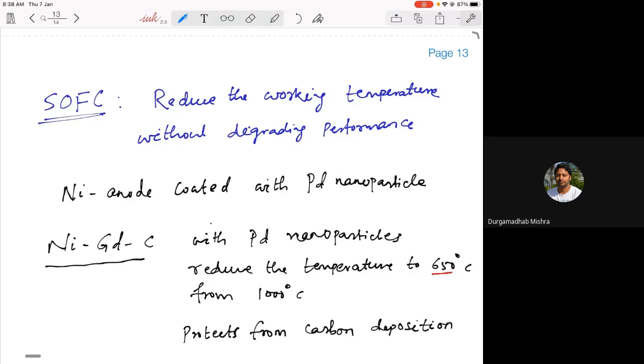Moreover, palladium nanoparticles also protect against the formation of carbon deposition on these electrodes. When you are operating at high temperatures with a nickel-based anode, if you have pure hydrogen fuel, it is good, but it is always mixed with some other hydrocarbons, and these carbon materials can get deposited on your electrode material, which normally reduces the life cycle of the fuel cell. They will degrade your electrode material as well as the catalytic properties. By putting in palladium nanoparticles, you can get rid of this carbon deposition as well.